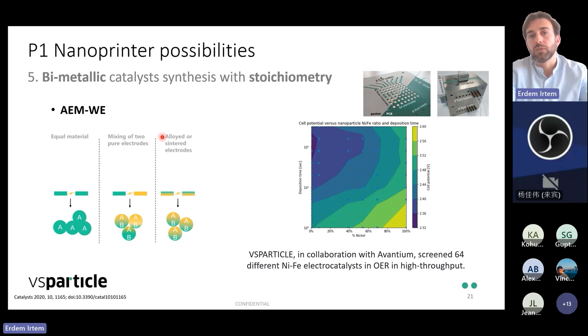For the alkaline exchange membrane water electrolysis, we already have a paper which was published around two to three years ago, in collaboration with Avantium and several academic partners, where we investigated nickel iron combinations and checked their onset voltage for water electrolysis in alkaline media. This was conducted on 64 different samples, analyzed in a high-throughput electrolyzer system that Avantium has. VSP's contribution was to realize those catalyst particles on those 64 spots, using the patterning capabilities that I explained in the earlier slide.